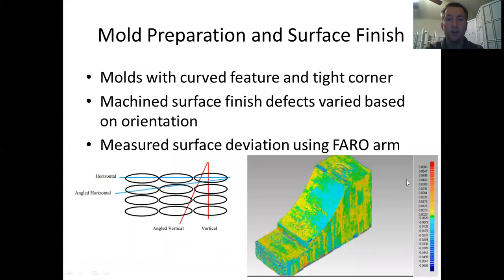Those same researchers also took a curved part and with a little bit more detail, and they machined it to get a relatively smooth surface. And they found that the orientation that the part was printed in and the angle that they were machining, they would have different surface defects just based off of the angle. And because this was used in BAM, it was oval roads that were being laid down. And then they also used a FARO arm to measure before and after, so they could compare the deviation of the surface as they pulled parts off of it.